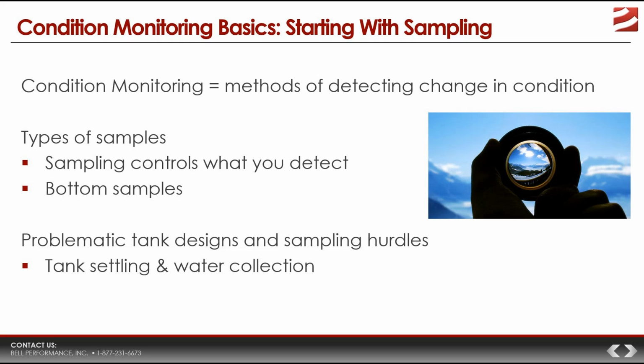It's very common for, over time, the hydrostatic pressure, the weight of the fuel, the thousands of gallons of fuel in that tank, to actually cause the bottom plates of the tank to deform and change shape. And so if they change shape relative to the shape of the tank bottom itself, that creates spaces for the water to pool and collect over time.